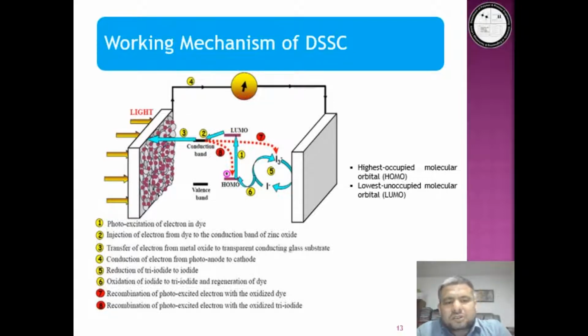They pass through a mesoporous thin film of semiconductor and finally collect at the conductive substrate. So electrons from the photoanode then reach the counter electrode through an external circuit, as you can see in the figure. Meanwhile, the electrolyte regenerates the oxidized dye and then diffuses towards the counter electrode. At the counter electrode, a reduction reaction takes place and the electrolyte is regenerated here. So in this way, the working cycle of DSSC is completed.